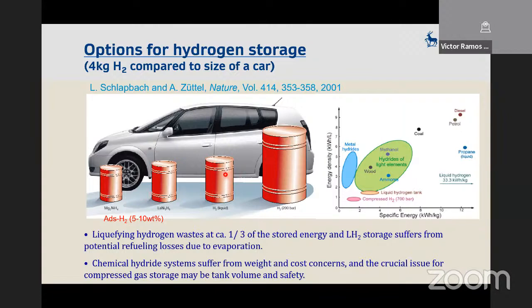But if you use liquefied hydrogen, you will lose 1/3 of the energy during the production of the liquefied hydrogen, handling, evaporation, and then the cryogenic energy you require. And then, therefore, solid state, which is, let's say, metal hydride here, gives you 5 to 10% weight energy, and that is very promising. But then you have a different problem. You have to drive the hydrogen off to fill the fuel cell.